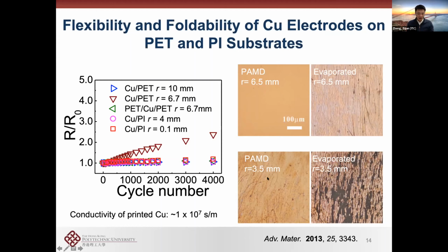The resistance doesn't really change much. It roughly changed by 5%, and this is typically because of a slow oxidation of copper in the air. It's not because of the material cracking or any other issue. And so this is great. It's very crack-free, and the film doesn't fracture, and doesn't come off from the surface.